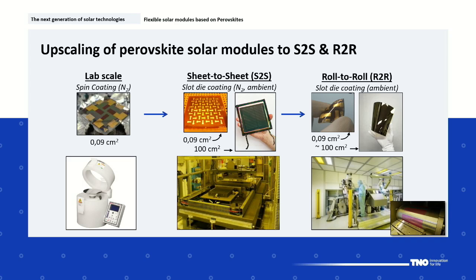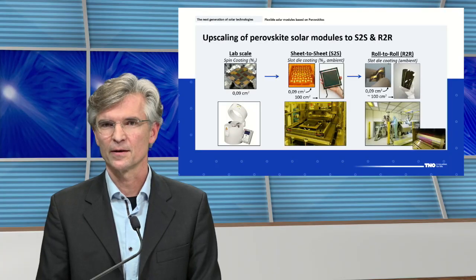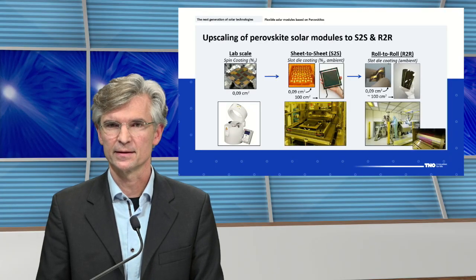The next step is then towards roll-to-roll processing. And again, we start with a similar device architecture so that we can compare the performances on the different length scales and process methods. And at the same time, we can also make the mini modules of about 10 by 10 square centimeter. For this, we use a pilot roll-to-roll line at TNO.